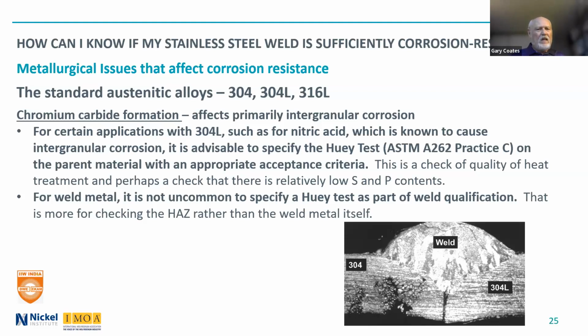So for weld metal, a lot of the same companies that want it on the parent material will ask for it to be done on weld samples that you provide. And again, for the most part, it's not the weld that's going to fail. It's going to be the heat affected zone that is going to, if anything, suffer any corrosion. The picture shows an old picture of a weld in 304 that had relatively high carbon, and 304L with low carbon, that went through the Huey test. You can see the high carbon one has that intergranular corrosion there.